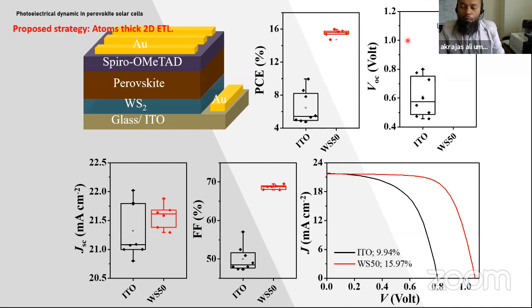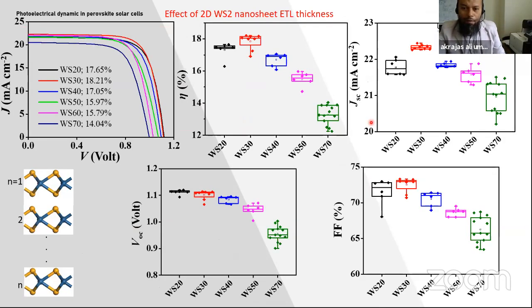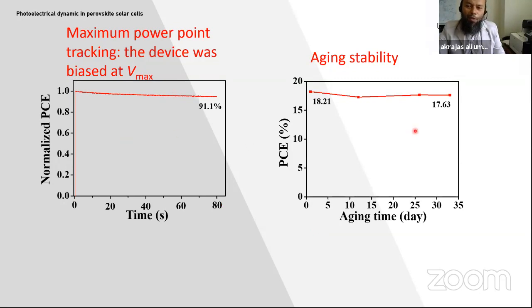And the VOC is also quite high, more than 1 volt, much higher than on ITO only. We evaluate how the thickness of the tungsten disulfide, meaning the number of layers, matters. We vary the thickness from around 5 monolayers to more than 20 monolayers. We got the optimum condition at around 5 to 6 monolayers, with efficiency reaching 18%. The VOC is also quite high, around 1.1 volt, and the fill factor is much higher, more than 70%. This is the typical operational stability.